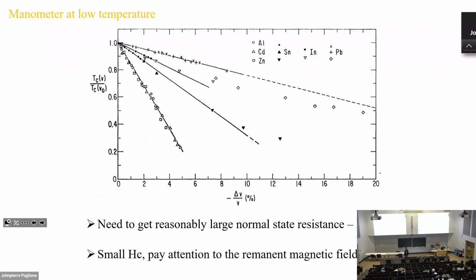For low temperature, we typically put in a superconducting sample and measure Tc. All those conventional superconductors have a well-defined Tc dependence. So typically you can put in lead, sometimes tin. The important thing is you want to make a really good measurement of the normal state resistance. The metals are really metallic, so the normal state resistance can be very, very small. So what you want to do is make a really long and thin wire. And sometimes you even use a hammer to abuse it and try to increase the normal state resistance, but hopefully Tc will not change. Another thing is, for this type of superconductor, the Hc is typically very small. So if you have a remnant field, that can change your reading of the pressure. So typically, you also want to scan your field from negative to positive and really find where your zero field is.